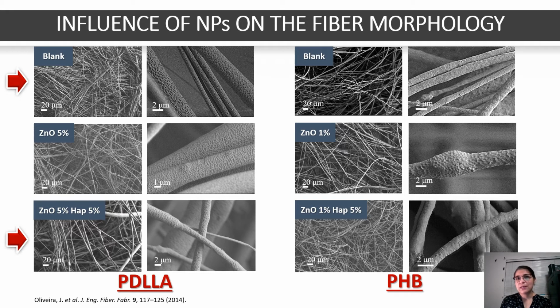Based on this result, it could be considered that the surface appearance is mainly determined by the nature of the polymer solvent combination. In relation to the fiber uniformity, thinning points are evidenced, possibly due to the heterogeneous distribution of the nanoparticles along the fibers, as well as the pseudoplastic characteristic of the polymeric dispersion. In the uniaxial stretching process of the polymeric fluid, the molecules are forced to align themselves in the direction of the applied stress. However, when the fluid is elastic, the aligned chains tend to relax to the original non-aligned conformation, a behavior that could counteract the formation of homogeneous fibers.